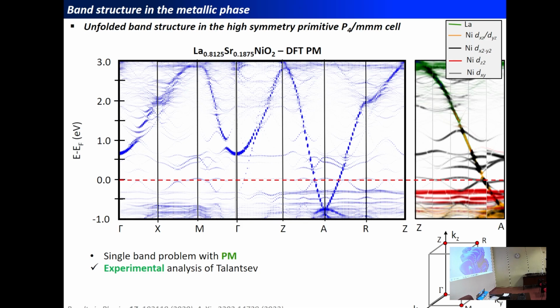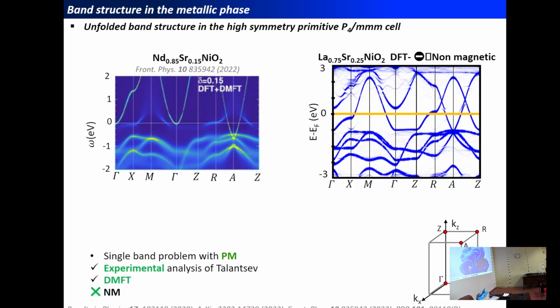This study took all the available experimental data and fitted it with different models and found that it should be a single-band problem. And so our DFT band structure also closely matches what we get from dynamical mean-field theory calculations, which are more elaborate techniques, in which they also observed a single-band problem centered at the A point of the Brillouin zone. But this is in contrast with the usual non-magnetic approximation used in the literature, which predicts a two-band problem, with two bands contributing around the Fermi level.